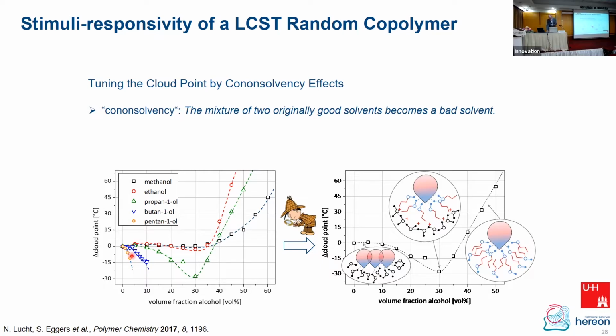It precipitates. But if you look at methanol and ethanol, first you see a slight increase of the cloud point, and then again a slight decrease with higher alcohol concentration. And at high alcohol concentrations, you actually see an increase of the cloud point. All of a sudden, the world changes, and what was bad before becomes good. That's why I call these polymers to be in a drunken state. And it's alcohol, obviously, so they behave a little bit funny.